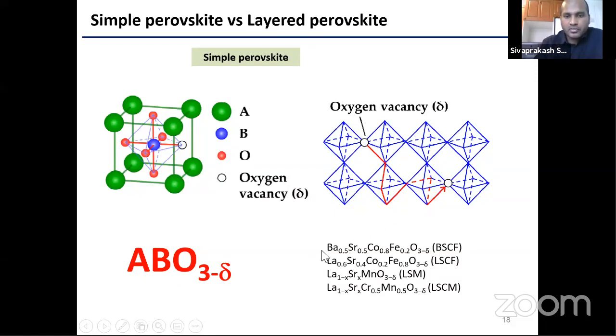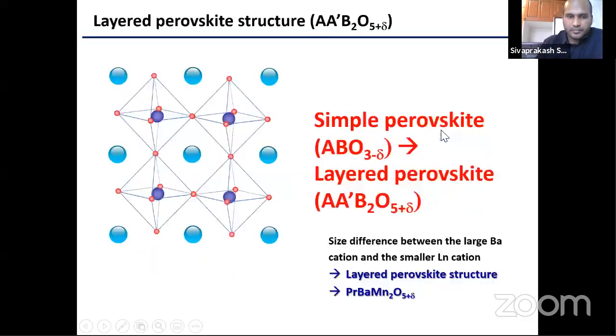Various examples of simple perovskites are shown here. Barium strontium cobalt iron oxide—barium is on the A site, strontium is also substituted on the A site, and cobalt/iron is the transition metal on the B site. Similarly, lanthanum strontium cobalt iron oxide has lanthanum on the A site and cobalt/iron as the transition metal on the B site. Lanthanum's oxidation state is 3+, and strontium's oxidation state is 2+. So doping a lower valence state on the A site, within the lanthanum site, creates the oxygen vacancy, which is the main pathway for oxygen ion conduction.